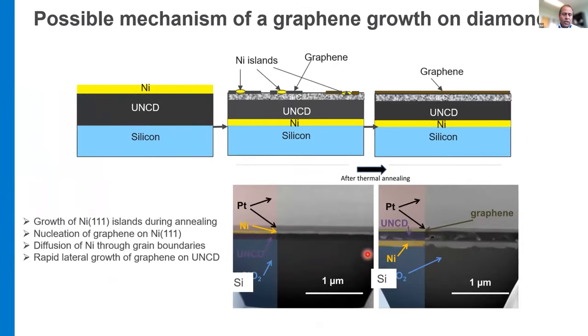So the probable mechanism that we think is that during this annealing process, there is a growth of this nickel 111 island, and then immediately, because the carbon beneath acts as a carbon source, it converts into amorphous carbon and forms these graphene rings, which grow very rapidly, laterally. And then the nickel does its work, goes through the grain boundaries and sits at the UNCD and silicon interface. And that's why we don't see any traces of nickel on top.